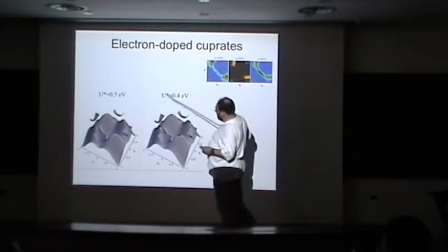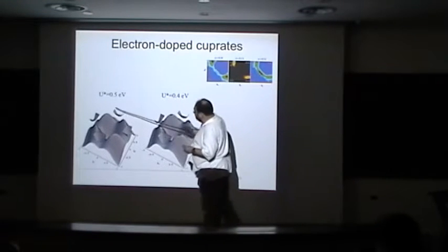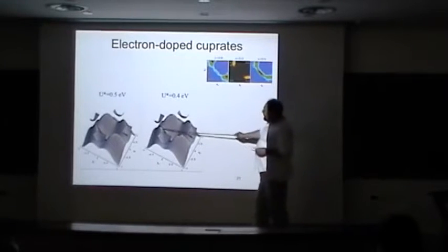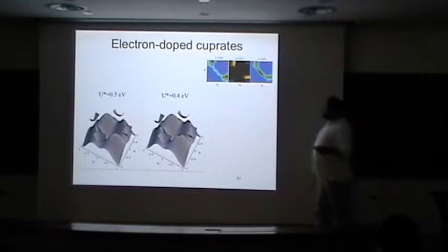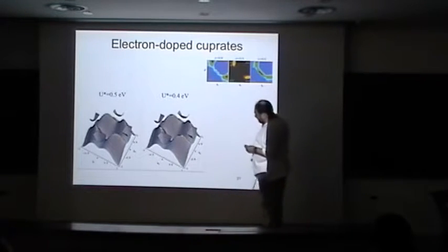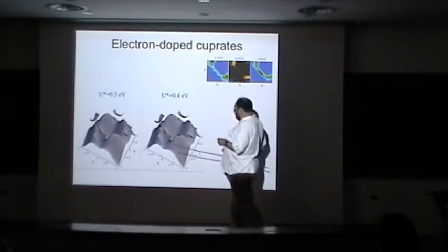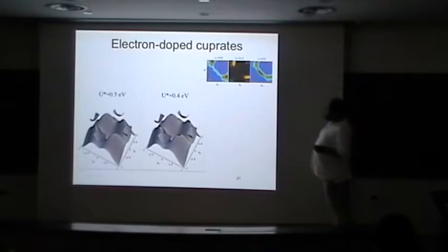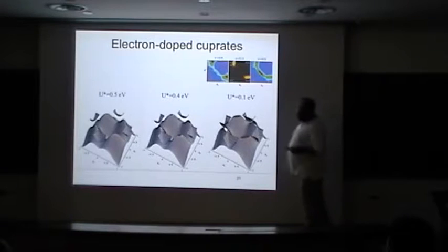Now if we cut it with the Fermi surface, the cut really depends on how big the gap is. So in this case, only the electron pockets are seen, and then at some doping, we get the hole pockets. It turns out that when we get the hole pockets, the superconductivity occurs. So there's no superconductivity here. The superconductivity starts where a small pocket opens up at pi half, pi half. And then it grows, and eventually it becomes one band.